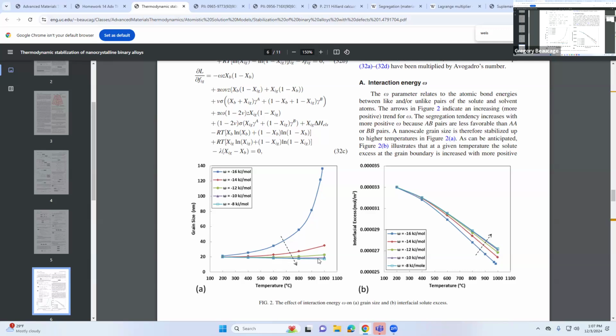It kind of makes sense. Like you have the second phase being driven to the interface because it wants to get out because it's not mixing as well. Right. So it preferably goes to the interface. It's negative, so it would normally mix, but because there's an elastic penalty, because it doesn't fit into the lattice, it wants to go to the interface. So the elastic is what's driving it to the interface. That's what this is saying. The enthalpy is hurting here because it's the negative enthalpy of mixing. And then it's against temperature, and this is the interfacial excess. So how much goes to the interface? As you make it less compatible, more of it goes to the interface. That kind of makes sense.